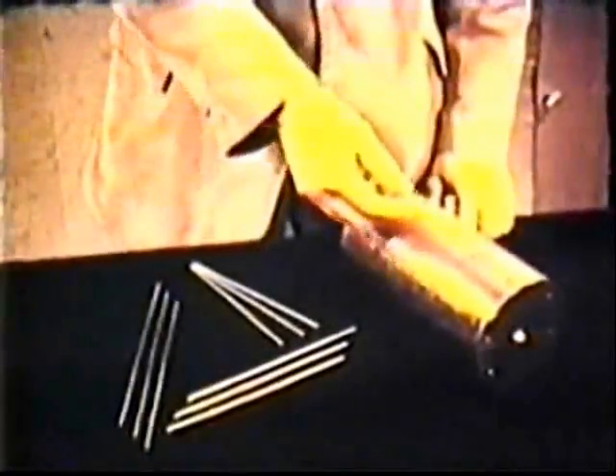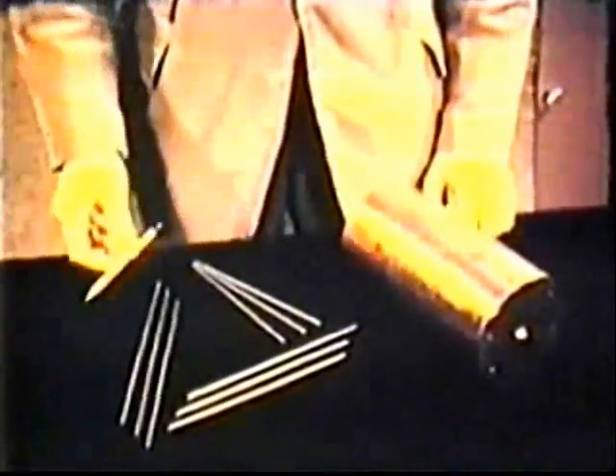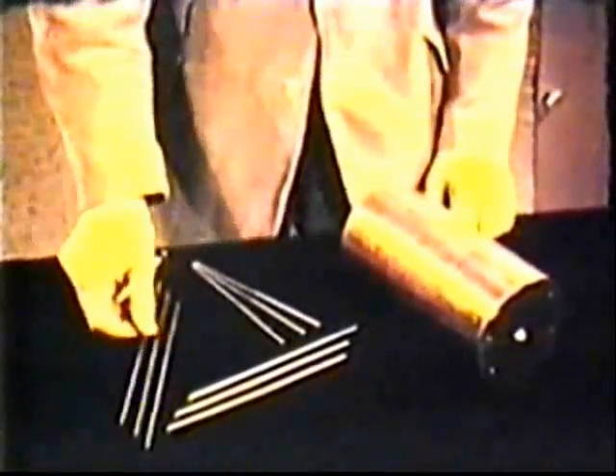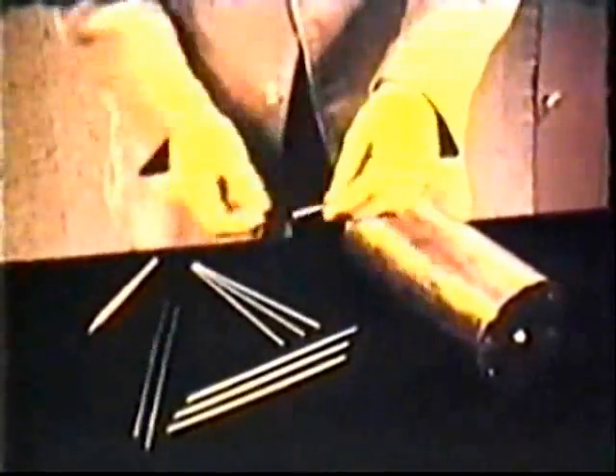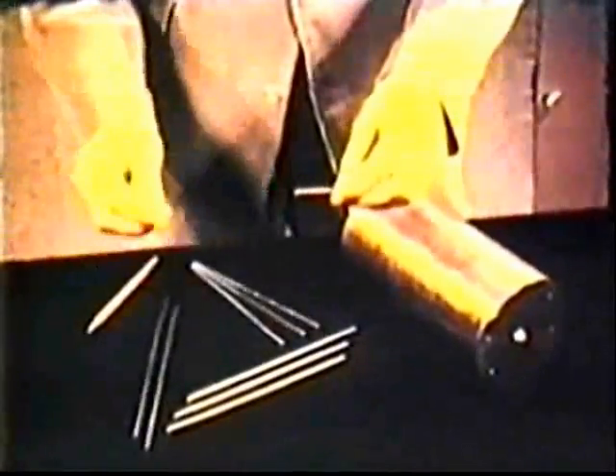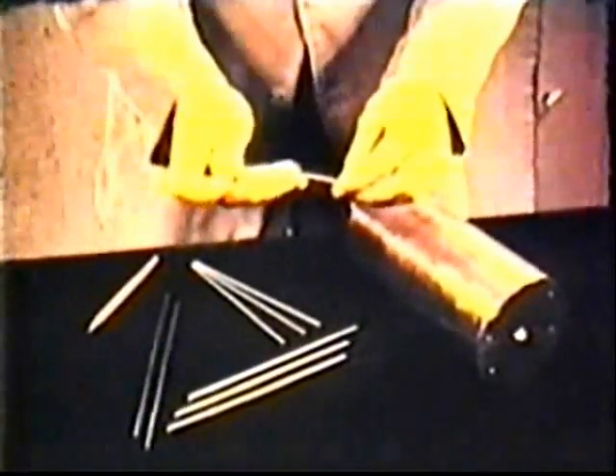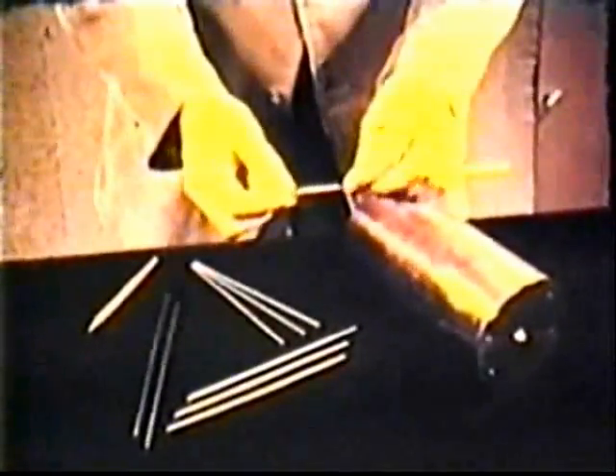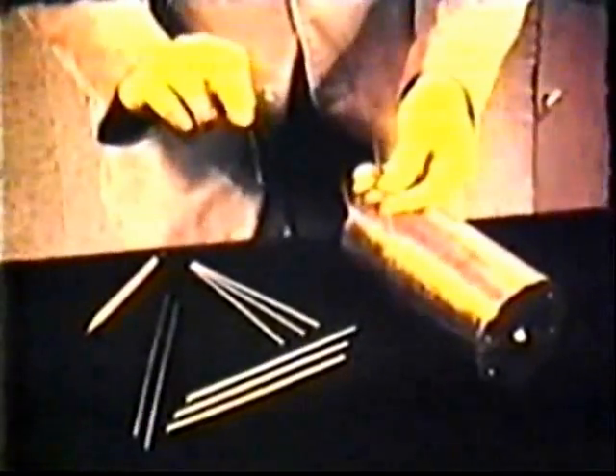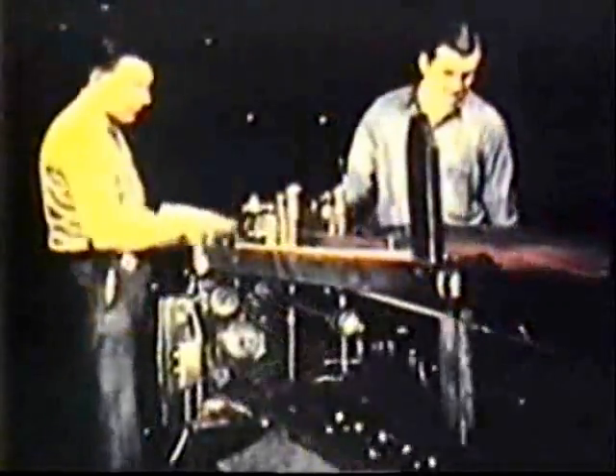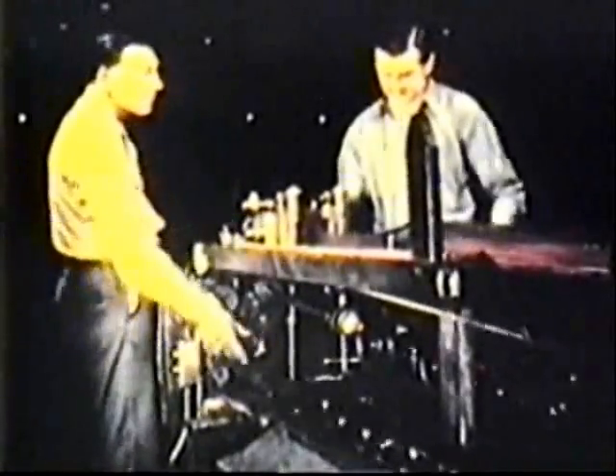And so, from a solid block of pure copper, and as the result of many separate and distinct drawing operations, we have now produced a capillary tube. This unique series of tubes, the smallest of which has an inside diameter of only 26 thousandths of an inch. Truly an engineering accomplishment. Because of the drawing operations, the tubing does not remain completely straight, and to correct this